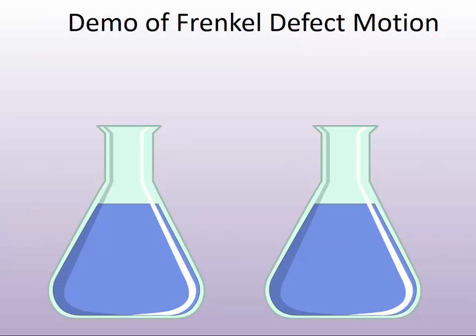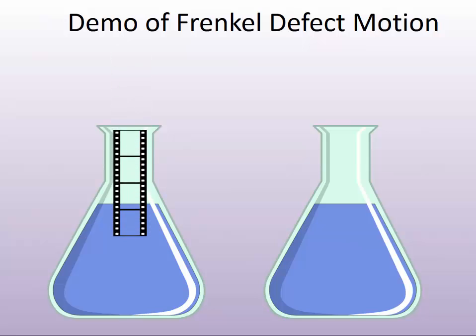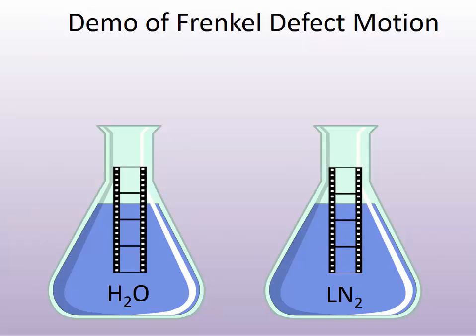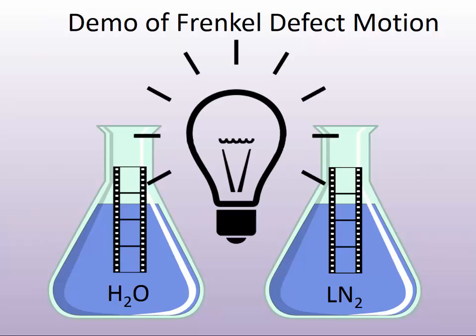This temperature is cold enough to freeze the atomic motions of ions in the crystal. To demonstrate the Frenkel effect, I had them lay a strip of photographic film in a pail of water, and next to that, a strip in a bath of liquid nitrogen. Liquid nitrogen is colorless, so it looks like water except for the temperature difference. Then I had them do something very unnatural — turn the darkroom lights on and leave them on for a good minute.